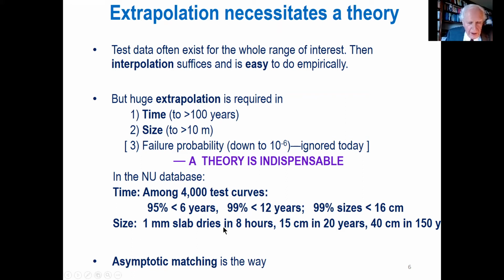Now, this is very important because of drying. There's a diffusion problem, and I should point out that 1 millimeter slab of cement paste dries within about 8 hours to uniform humidity. 15 centimeter specimen takes about 20 years to dry. 40 centimeter specimen, about 150 years. And of course, when you go to 1 meter, it is millennia.